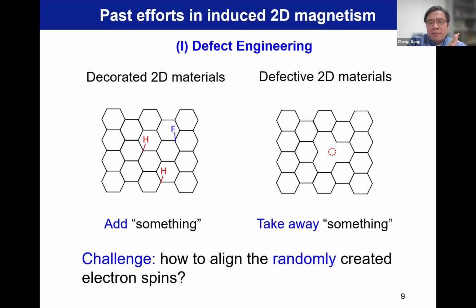So in the early days, even since the discovery of graphene, many efforts were made trying to find long-range magnetic order. There are three main types of effort. One is defect engineering. Basically, in graphene, molybdenum disulfide, or whatever non-magnetic 2D materials, you can either add some elements onto the 2D crystal or take away some atoms. So you add something or remove something. You can always easily create spin moments, but they are local. It's very hard to align them.